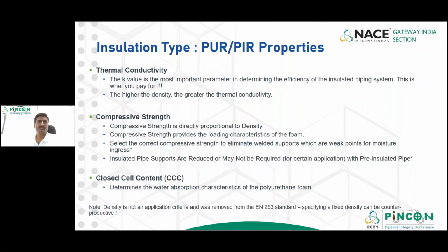The third factor is the closed cell content. This determines the water absorption characteristics of the polyurethane foam. Generally, it is greater than 90%.